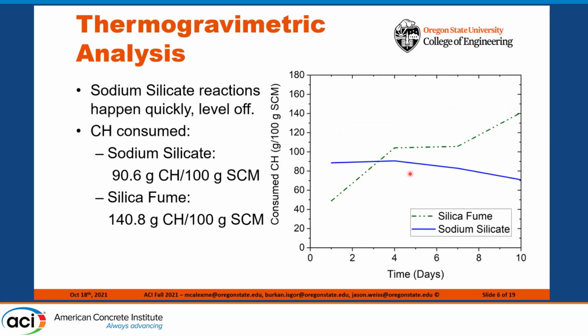We are using the highest value of CH consumed for the sodium silicate, even though the values drop off slightly moving towards the 10-day reading. Our theory is that the pozzolanic reaction is so quick that we're possibly losing the KOH buffer within the test, which is affecting these results.